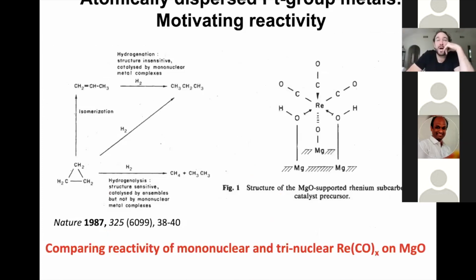Second, some motivation. So obviously when you're trying to figure out whether or not a class of materials is worth studying in lots of different detail, you would want to convince yourself that there's some interesting properties to motivate detailed studies. And so I highlighted just one or two studies from some time ago showing interesting reactivity of atomically dispersed metal catalysts. So this is a classic paper from Bruce Gates's group. What they looked at is they looked at mononuclear rhenium species on an MgO support. These were carbonyl species. And then they compared these mononuclear structures to a trinuclear species, so 3 rhenium atoms at the same time. Effectively, what they found is if you feed cyclopropane to these catalysts, whether you have 1 atom or 3 atoms in your active sites, cyclopropane will isomerize to propene, and you can do some hydrogenation to make propane. This happens on both types of sites.